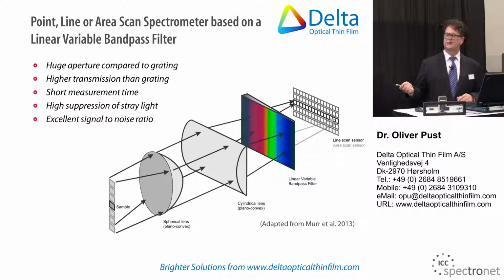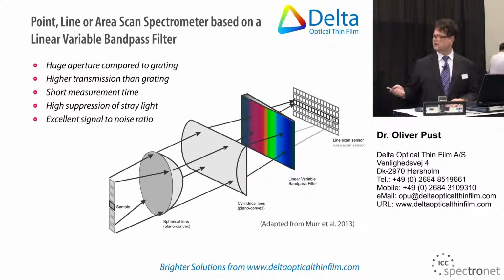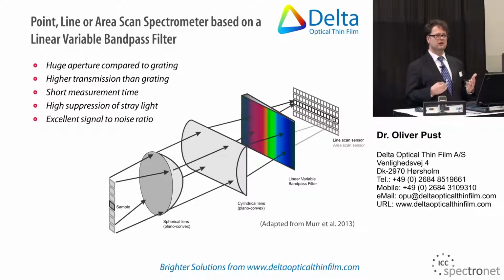These statements over here are actually not mine. These are taken from some publications from a group in Munich who have used a linear variable bandpass filter to make a point spectrometer, but also to make line scan spectrometers. And compared to a grating, it has a much higher aperture, so you collect much more light. It has a higher transmission efficiency, which allows for a shorter measurement time than if you would use a grating. Also, the suppression of stray light is at least one order of magnitude better than with a standard grating. And you have a very high signal-to-noise ratio.